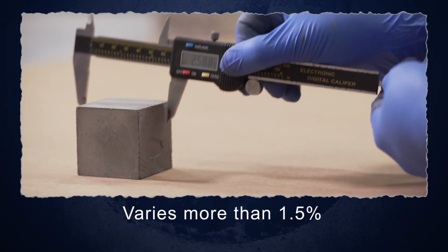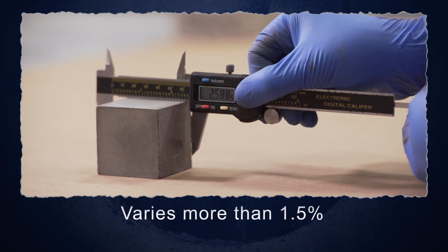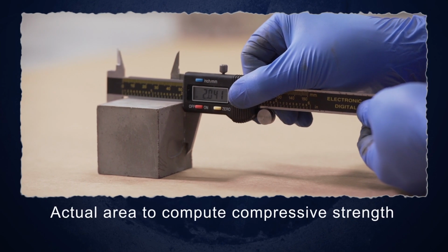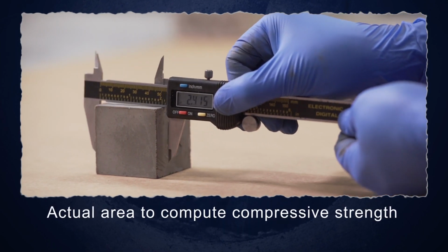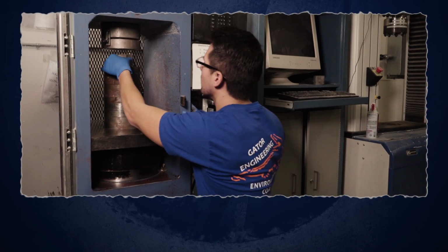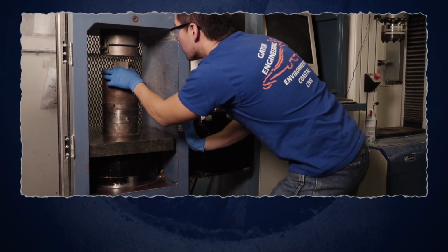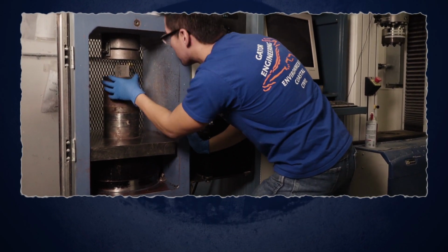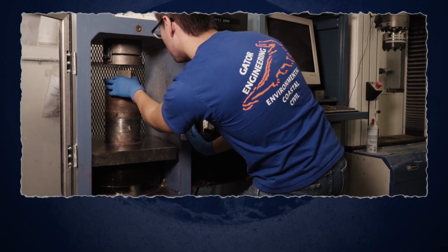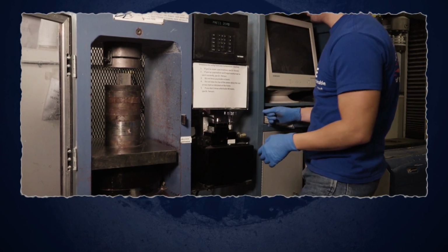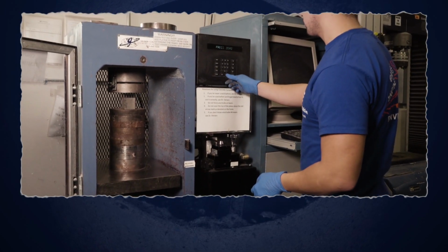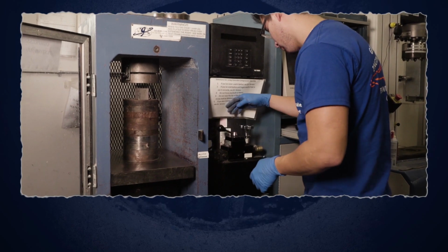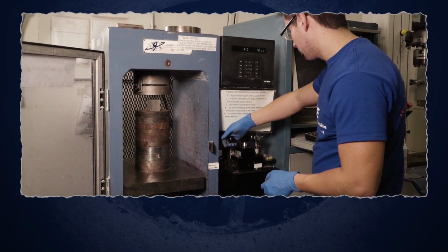If the cross-sectional area of a specimen varies more than 1.5% from the nominal, then the actual area should be used to compute the compressive strength. Carefully place the specimen in the testing machine below the center of the upper bearing block. Specimens should be placed such that the load is applied to specimen faces that were in contact with the true plane surfaces of the mold.